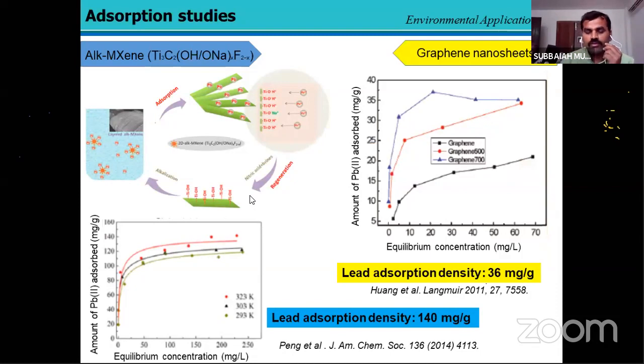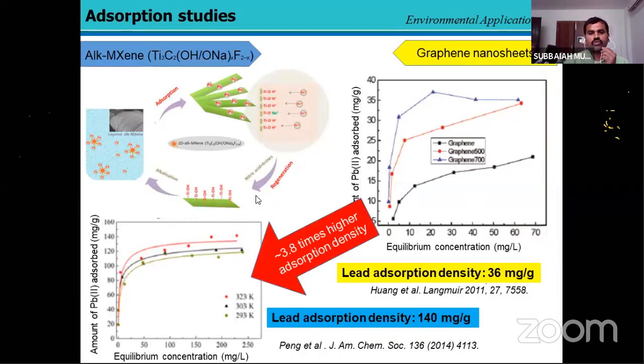We found that the absorption capacity was much higher, that means 140 milligram per gram using this sodium form of MXene, which was compared with some graphene-based materials, which show a lesser amount, like 36 milligram per gram, which is almost 4 times lower absorption capacity of graphene oxide than the MXene-based materials. This is quite an advantage of MXene-based material.